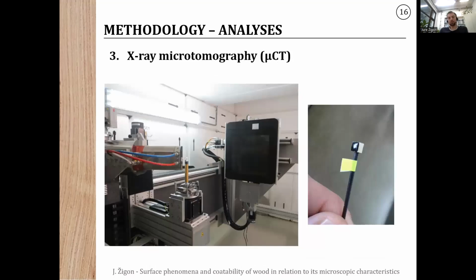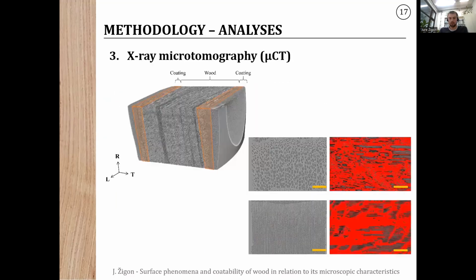The third technique which I was using in this case at Ghent University is X-ray microtomography. Again, here we were studying the penetration of the coating inside the wood. On the left side, we can see the photo of this equipment. Probably you know it. I won't go into the details. And on the right side, we can see the sample prepared for the analysis or the scanning. It's very small and needs to be properly prepared. And for that we are really precise and the results are the proper ones.